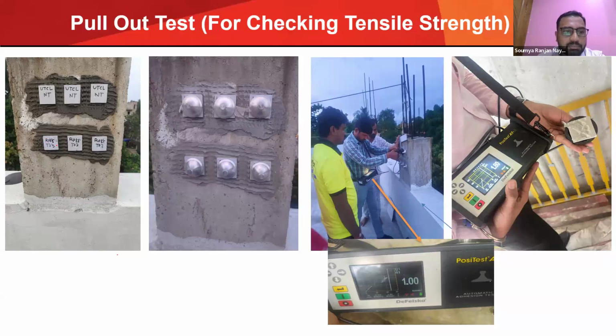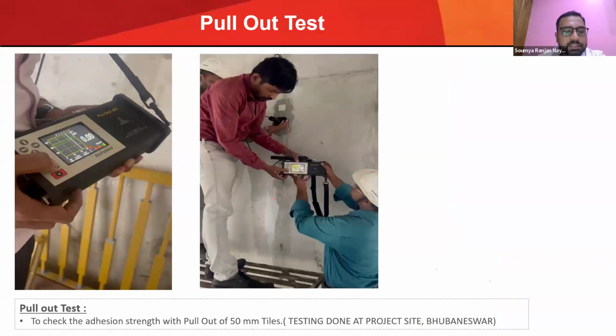We fix 50 mm by 50 mm tiles on the concrete surface with tile adhesive. Then we fix the dolly, which helps pull the tiles with a lever, and at what load the tile adhesive leaves the substrate and tiles is known as the tensile adhesive strength of this tile adhesive. Okay, let's look at the test.